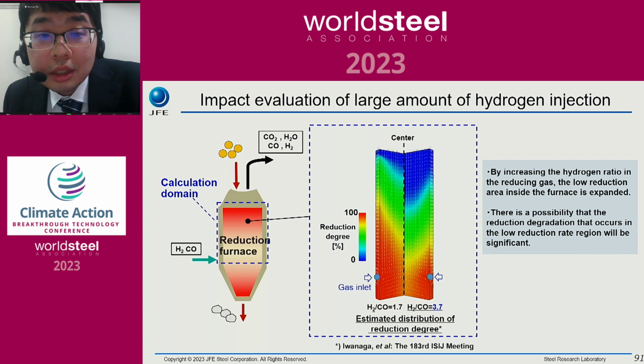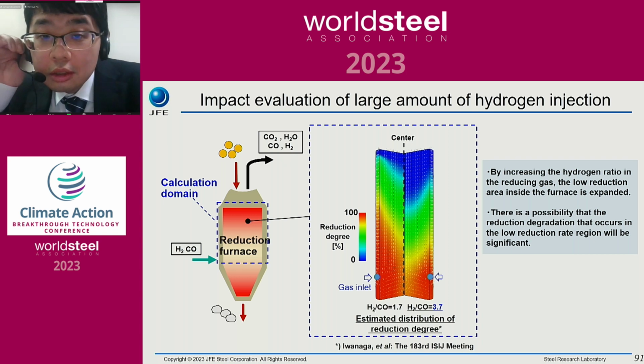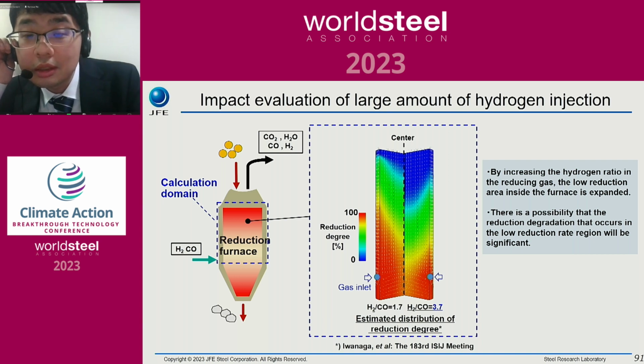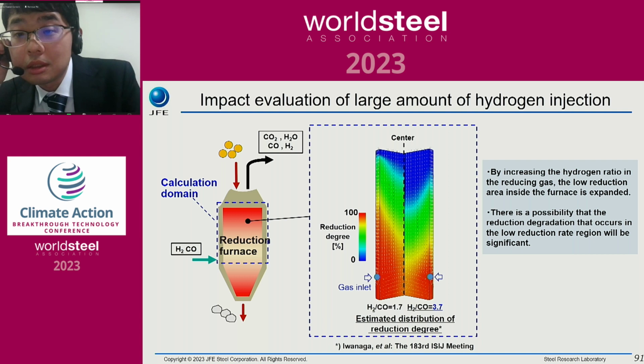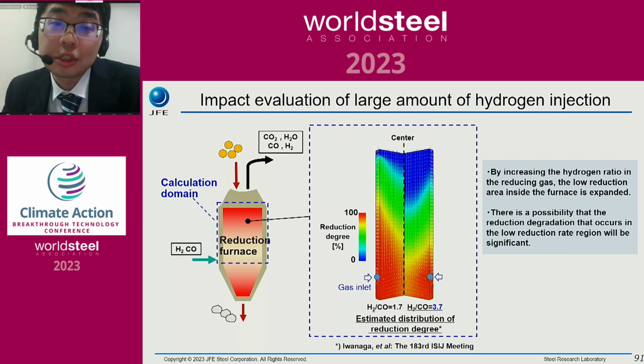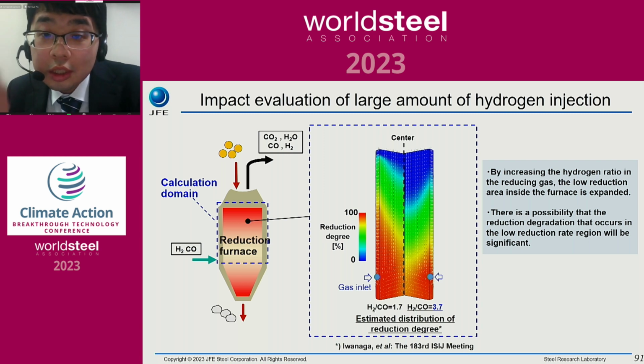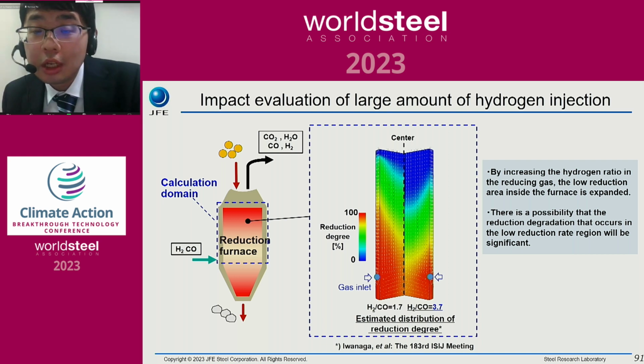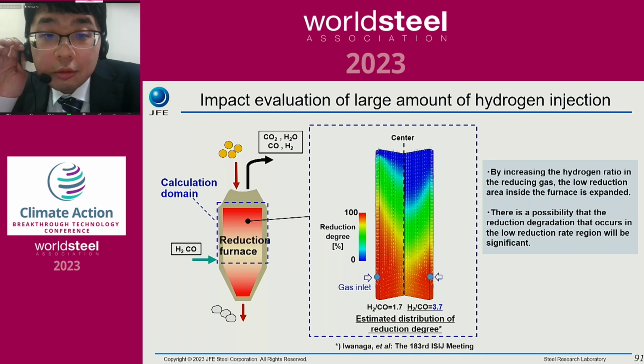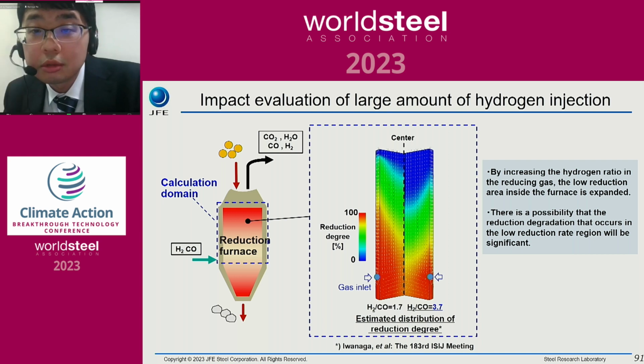And in this slide, this slide shows the effect of increasing the hydrogen ratio in the reducing gas on the distribution of the reduction degree in the shaft furnace. And this is an example of numerically simulating the reaction behavior in a furnace. The composition of the reaction gas is assumed for H2/CO of 1.7 and 3.7. And the center figure shows the calculated distribution of reduction degree.